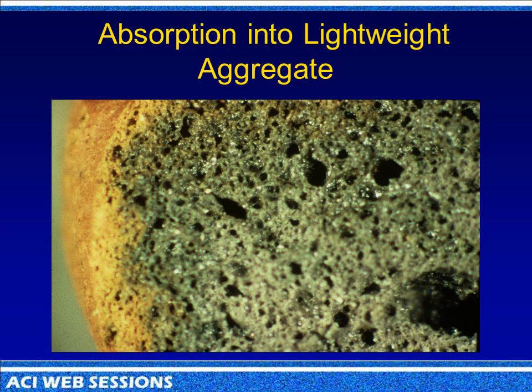This is just an aggregate. Now, the phrase we use is pre-wetted all the time. We don't use saturated because you can never really saturate a lightweight aggregate particle. Some of this stuff internally here will never fully saturate. And you get pretty good saturation, pretty good absorption, I should say, depending on the aggregate. Up to about 24 hours, it takes on water very quickly. And after that, it takes it on much slower. And then eventually, it will fully saturate.